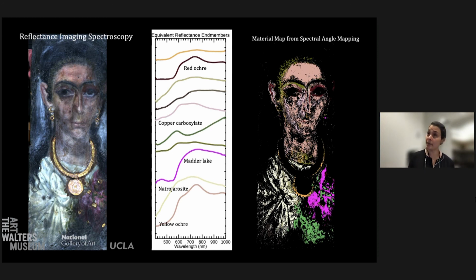We know there's copper in the painting. And then there's Madder Lake. But from this data alone, I cannot tell if there's Egyptian blue there. And so again, as we saw before, that's a limiting factor because it is a possibility. We know they're in Roman Egyptian portraits, and if it's mixed finely, we're not going to see it in the reflectance spectra.